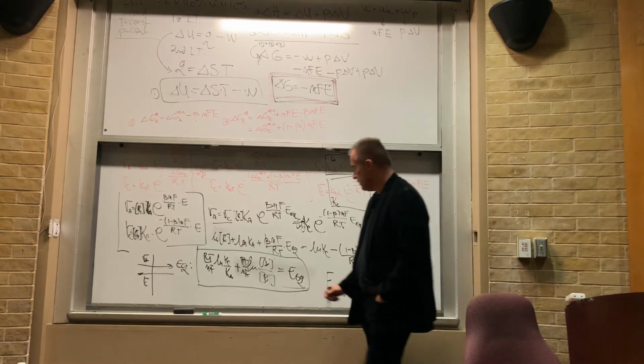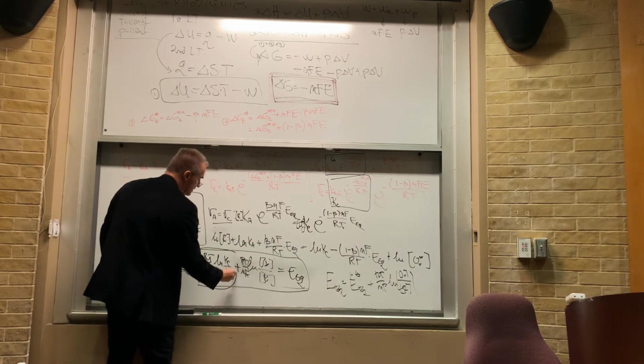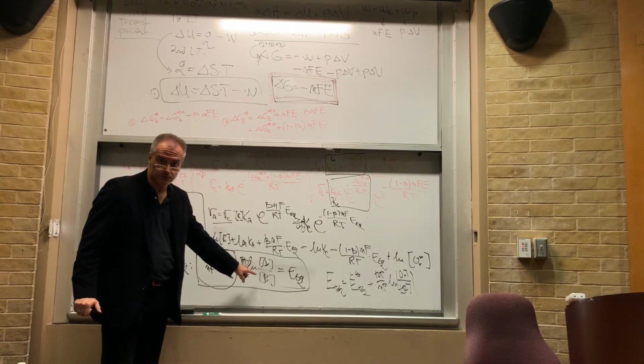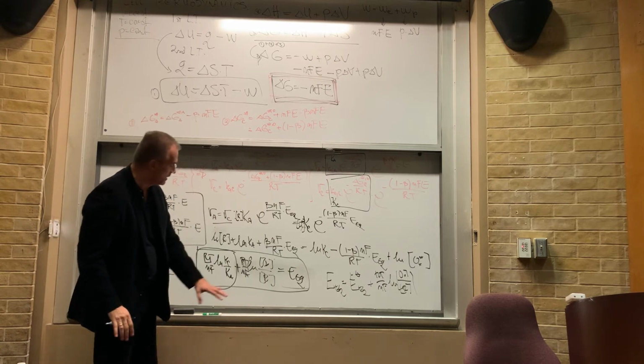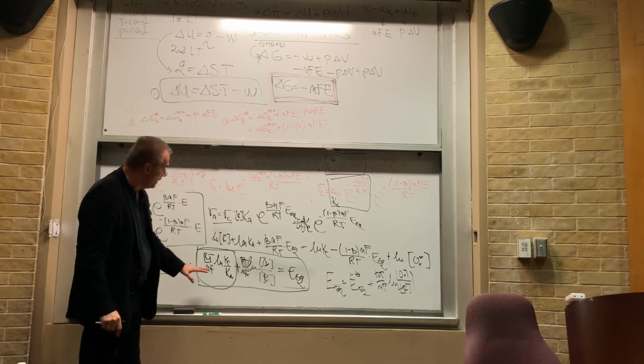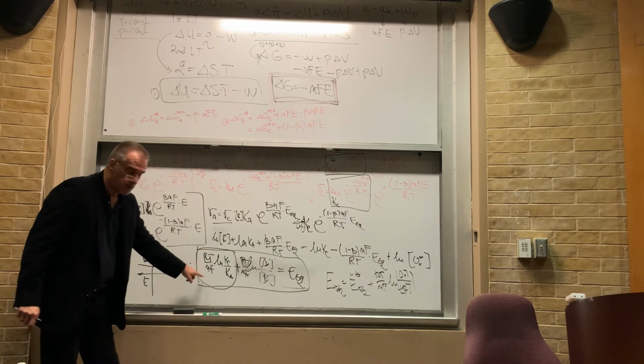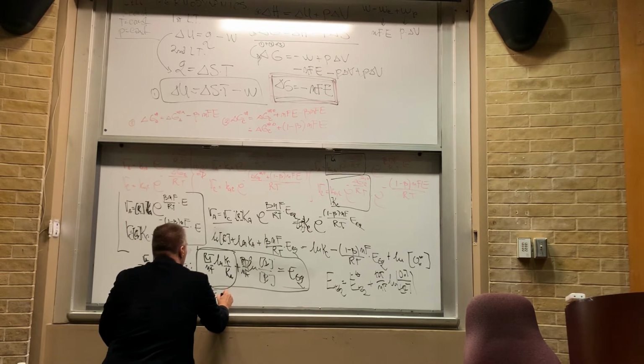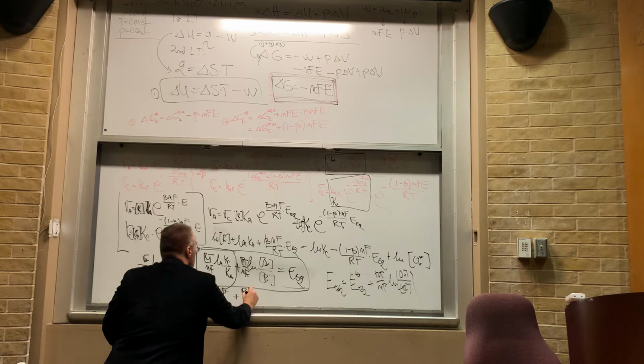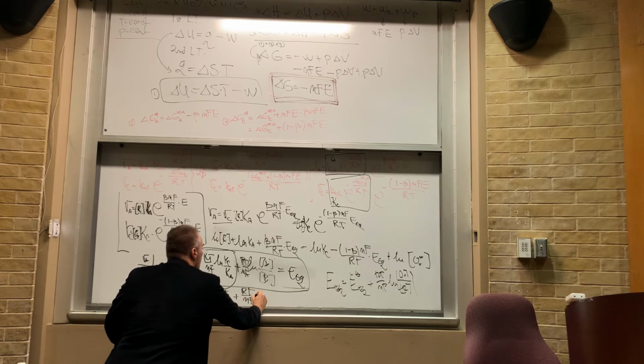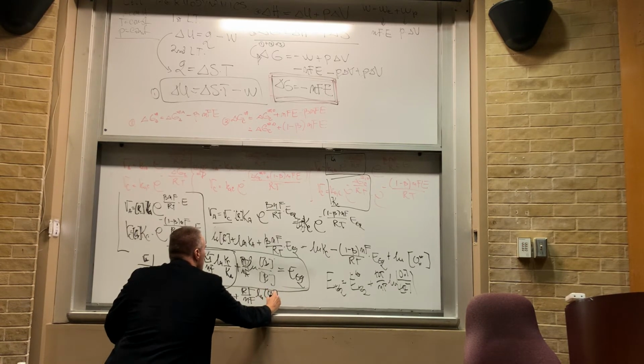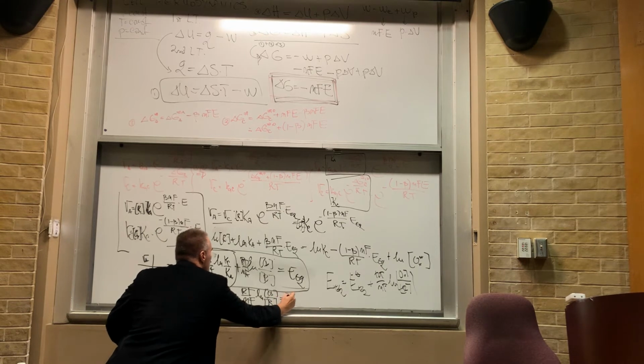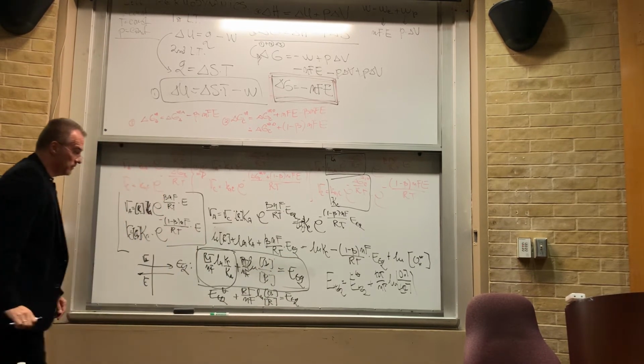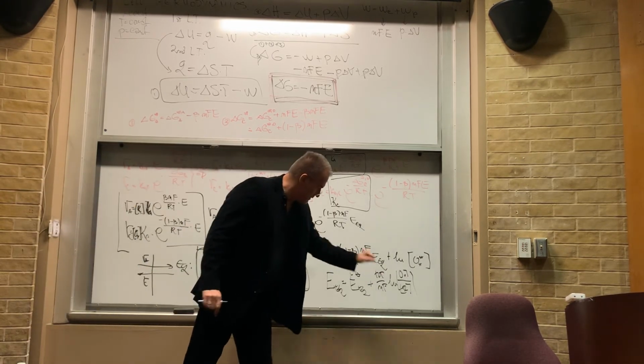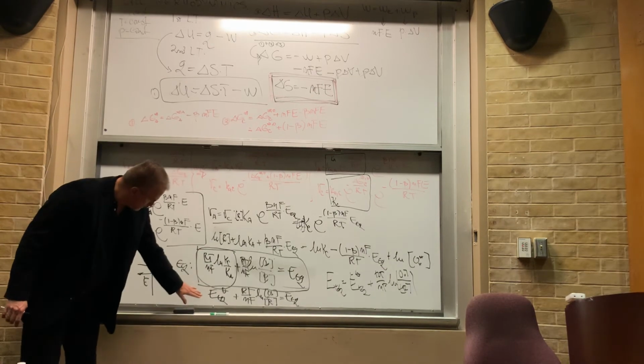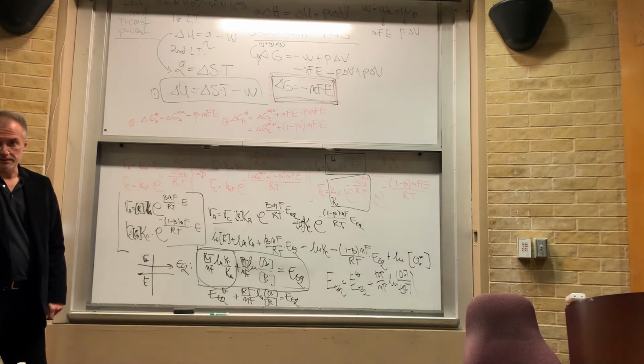That's standard notation. So obviously this term here, which is concentration independent, if I put 1 for the concentration of oxidized and reduced species, which is standard conditions by definition, this drops off, right? Because ln of 1 is 0. So I end up with the equilibrium potential being equal to this term here, which I'm going to call the equilibrium potential at standard condition, plus RT over nF ln oxidized species divided by reduced species concentration, is equal to E equilibrium. This is basically the same thing that we know from before. This is the dynamic definition, which uses a different approach to get to this point, but this is a Nernst equation coming from the kinetics, right?